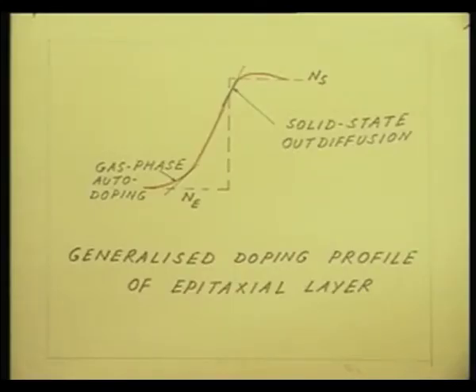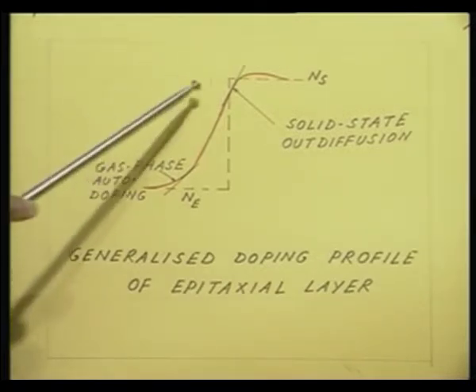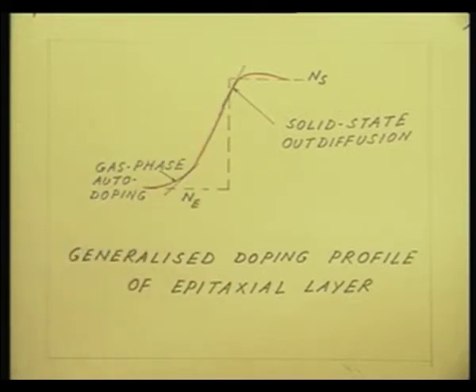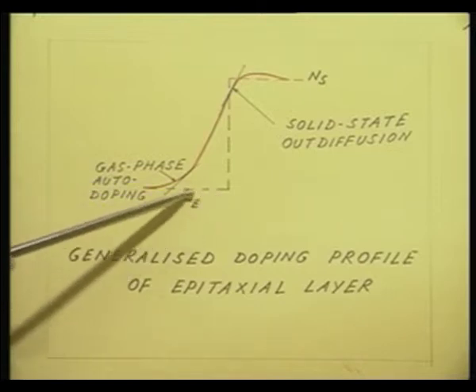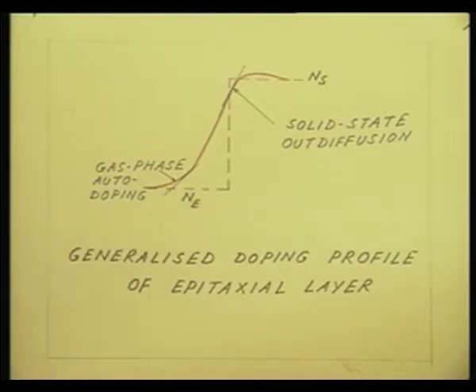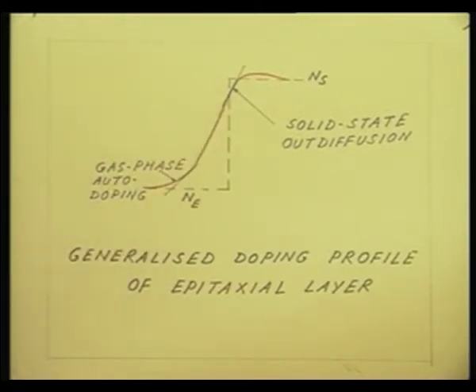If we look at the first card we have here today, the dotted line signifies the ideal abrupt junction between the epitaxial and the bulk region. Ne is the epitaxial layer doping concentration, Ns is the substrate doping concentration. Let us assume that they are both the same type, only the doping concentrations are different. In this particular case, I have assumed that the substrate is doped highly and the epitaxial layer is doped to a very low extent, it is almost intrinsic.